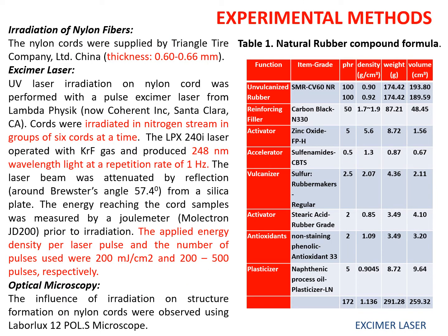The compound formula is shown on the slide on the right-hand side table, and the cords were supplied by Triangle Tire Company of China. The irradiation, as I mentioned, was done by using an Excimer laser by Lambda Physik. The samples were irradiated under nitrogen stream in groups of 6 cords at a time. Repetition rate was 1 Hertz. The applied energy density per laser pulse and the number of pulses were 200 millijoule per square centimeter and 200 to 500 pulses. We also use an optical microscope to observe this.